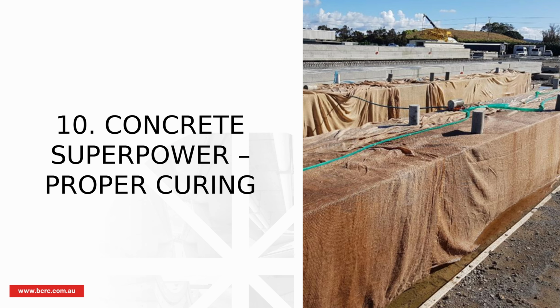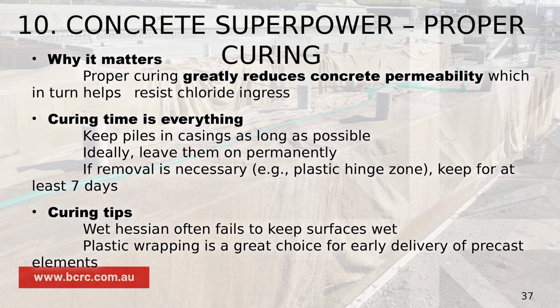Final lesson, concrete superpower, which is proper curing. Curing is everything for concrete, because curing reduces permeability of concrete, which in turn slows down chloride ingress, which in turn improves durability and longevity of the structure. Curing time is everything. Ideally, you should cure for at least 7 days. If you're dealing with pile casing, keep them on as long as possible. Ideally, leave them permanently if the design allows you to do so. Again, if you do have to remove them, try to wait for the 7 days before you do so.